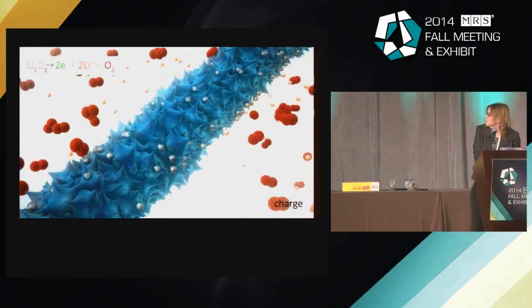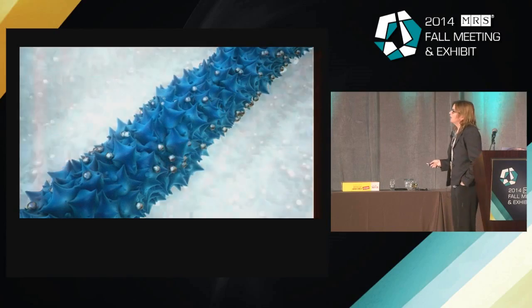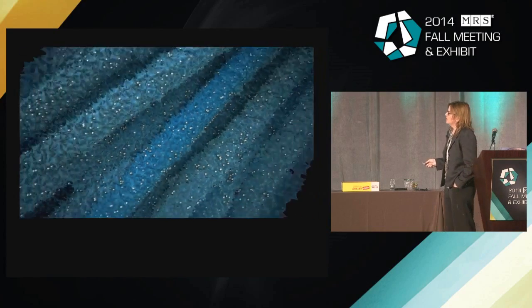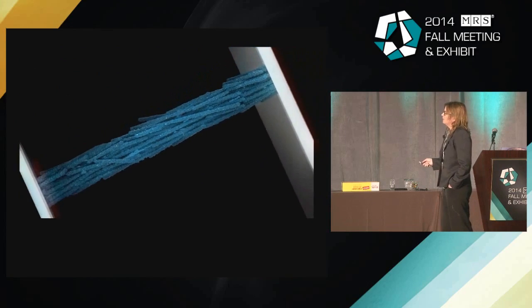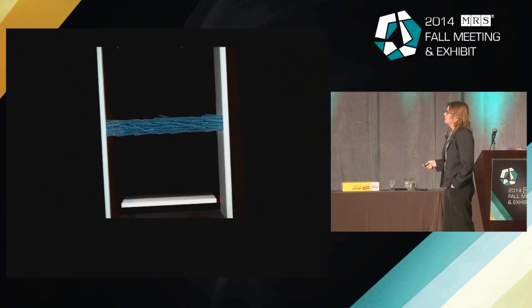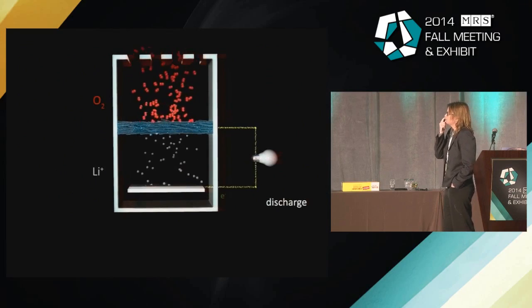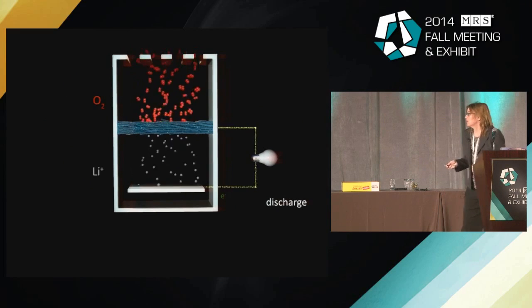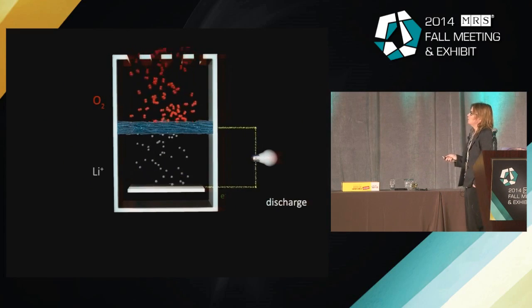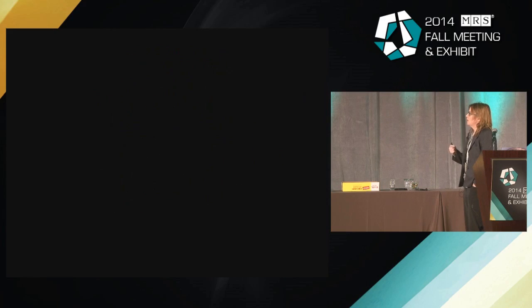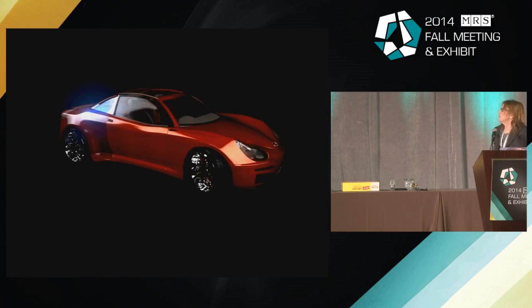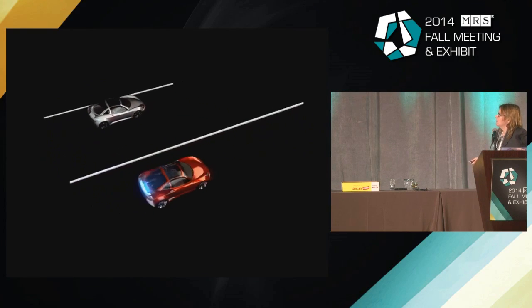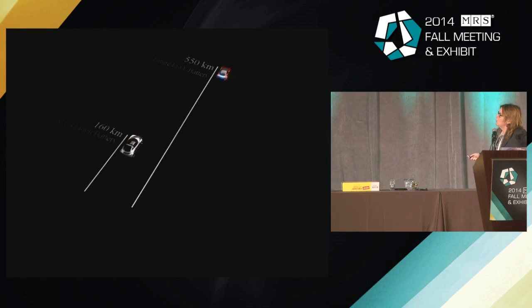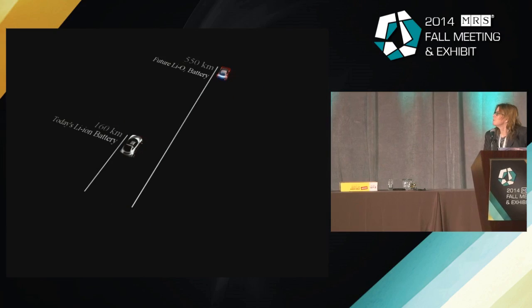Now you can take a lot of those and get them to self-assemble and test it as a lithium-oxygen battery in a system that would look something like this, where they self-assemble. And we showed that it was functioning, and at the time that we published it last year, had the best performance of a manganese oxide lithium-oxygen battery. And so here's my car. And no, it's not really, but what you would be able to do is greatly increase the distance between charges.